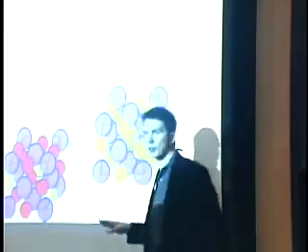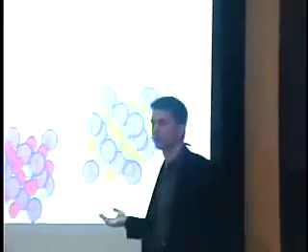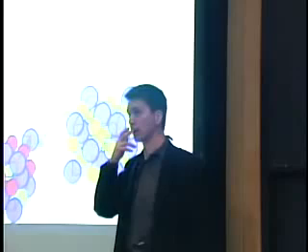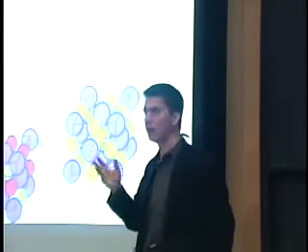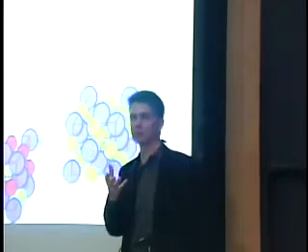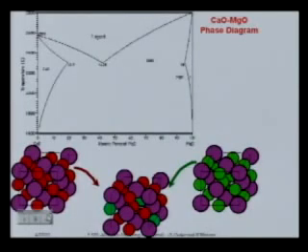And the octahedral interstitials of an FCC lattice also form an FCC lattice. So you can think of rock salt as two interpenetrating FCC lattices, one of cations, one of anions. So when you mix the two, you're essentially asking the question, at each interstitial, is there a calcium or a magnesium sitting there? So again, you have a perfect binary problem. It's a lattice model. But this already illustrates a nice thing about this approach. In your whole lattice model, the oxygens won't appear. So the variables you use are only going to be defined on the cation lattice.